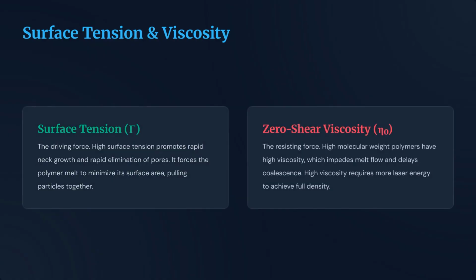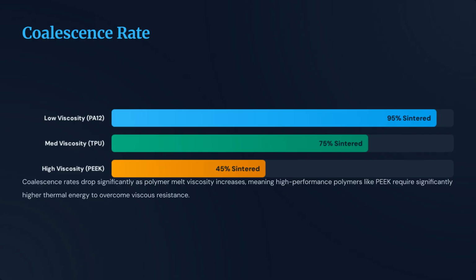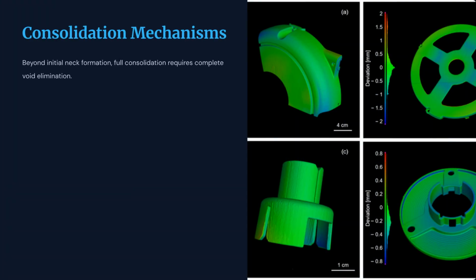Two key forces are at play: surface tension, which acts as the driving force for consolidation, and zero shear viscosity, which acts as the resisting force that needs to be overcome by laser energy. Ultimately, the coalescence rate decreases as viscosity increases. This means high-performance polymers, such as PEEK, require significantly more thermal energy to overcome viscous resistance compared to lower viscosity materials.